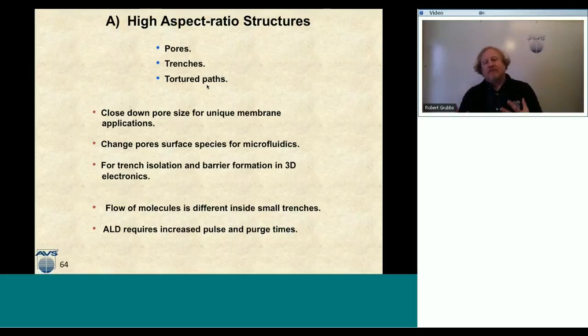So coating these high aspect ratios is actually very important, and it really enables their functionality. We can close down these pore sizes for unique membrane applications if we want to reject large molecules and let small molecules pass. ALD gives us the potential to do that. If we want to change the surface type, if we want to make a hydrophobic surface or a hydrophilic surface for microfluidic applications, we can do that by coating these high aspect ratios with ALD.